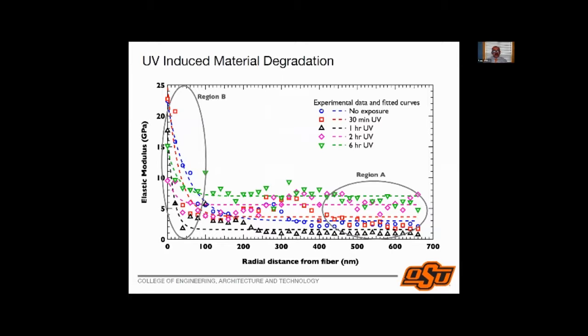If you can follow with me and look at the blue curve, this is the elastic modulus, and it is about 3 GPa when you're far from the fiber. You come to the interface region and the elastic modulus starts going up. Now, if I expose the same material to more and more UV, what I find is that the elastic modulus changes. First, it appears to decrease, and then it appears to increase depending on the exposure duration. I get a similar trend over here, that first it tends to decrease and then it tends to increase.